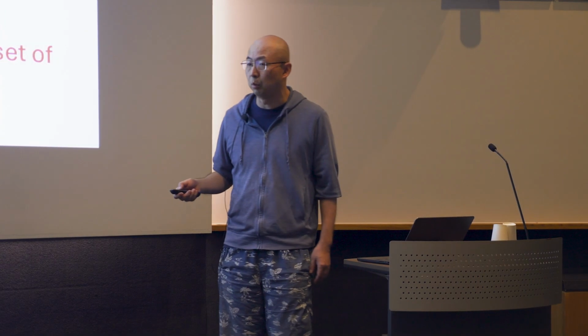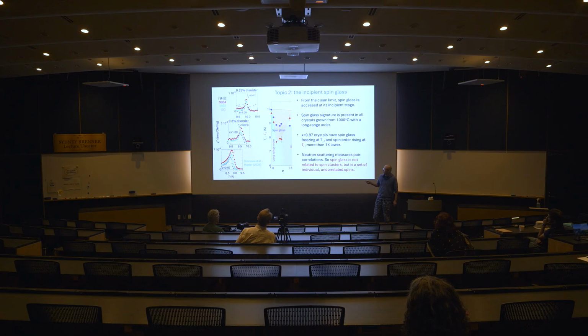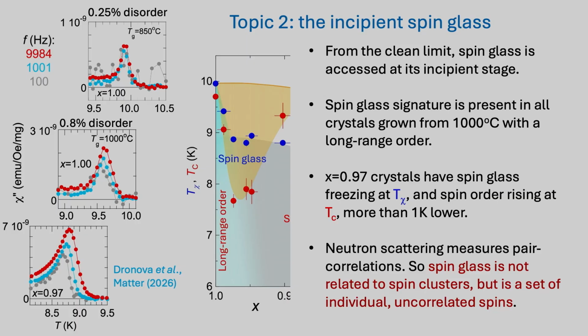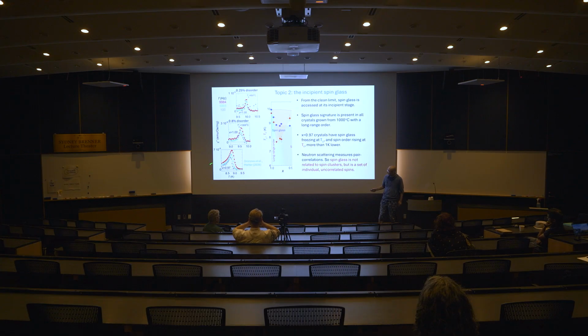The spin glass story turns out to be very quick once you understand this. If you look at the 850C growth, there's no frequency dependence in the magnetic dissipation, or at least no observable one, it's very small. In the pure sample, you start seeing a spin glass phase, with frequency shifting between different measurements. And at the 97% sample, you can see clear shifting of this spin glass behavior. However, we already know from our neutron diffraction that this is a long-range order sample. So the spin glass phase is not only associated with short-range order; it can also be associated with a system with clear long-range order as well.